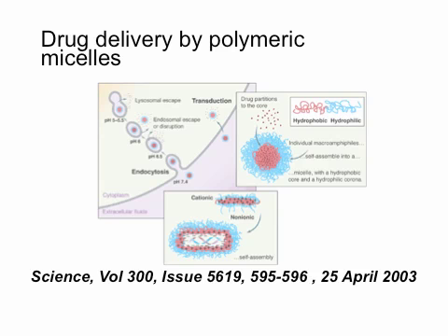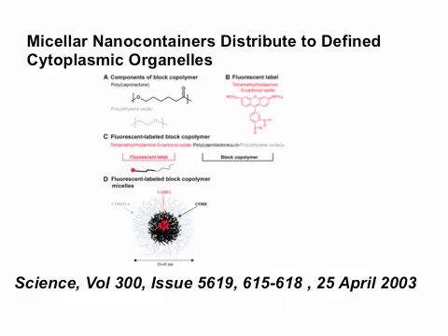Now, the other problem was the dilution. If you have a micellar dispersion, and I dilute it in an infinite pool of water, it becomes just separate blocks, and there is no micelle left. So that's another thing that you need to address. So maybe a micelle is a really bad idea overall. One way to address this is, for example, to cross-link your individual chains together, so that once they're formed, they can't disintegrate anymore. And that's done quite a lot.